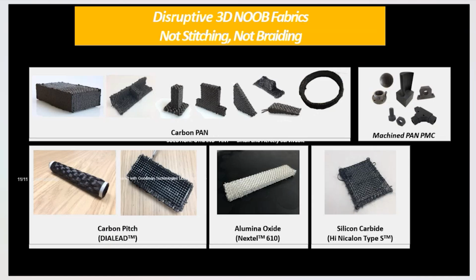Here's another type of fabric that is not knit and is not braided, but it is actually fabricated much like one would fabricate a tablecloth. And in this case, the 3D fabric, it doesn't use 6,000 or 12,000 or 24,000 needles to make the fabric. It uses 5, one for X, Y, Z directions, and one for plus or minus theta. And this new technology can be made to make 3-dimensional parts like you see here. It's been done in pan, it's been done in pitch.